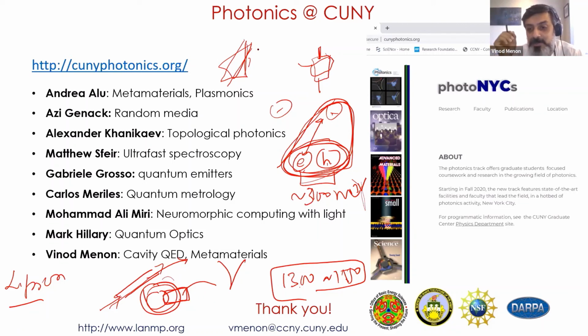In fact, the way people do it is you take a monolayer, you do a second harmonic generation, and the monolayer shows a very strong second harmonic signal, and you will get the crystal orientation from that, because such a structure will show some kind of a 6-fold symmetry if you do a polarization resolved second harmonic signal. And then from that, you can map the orientation of the crystal. Now you can take 2 of these crystals, and then you bring them next to each other, and you can do alignment. So there's a whole business in this twisting.